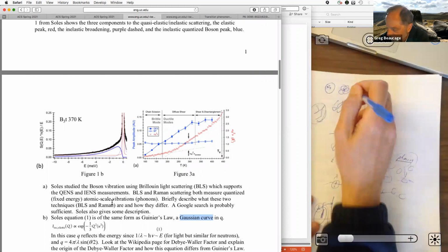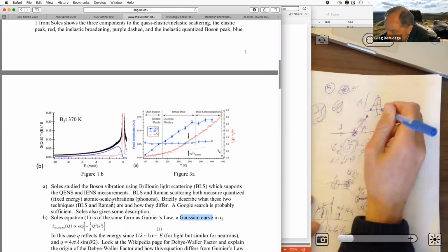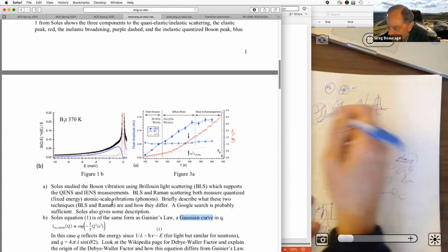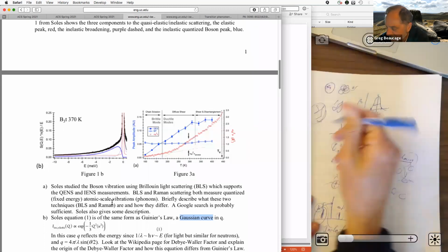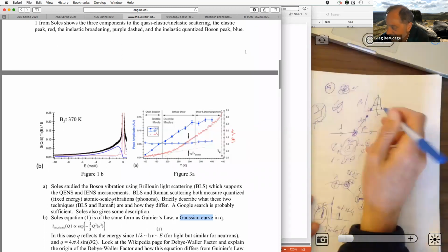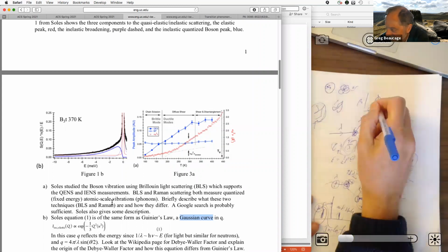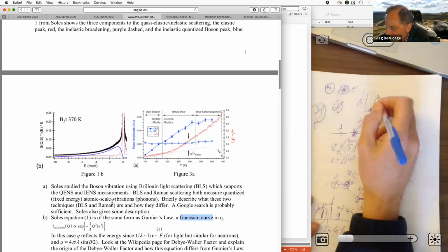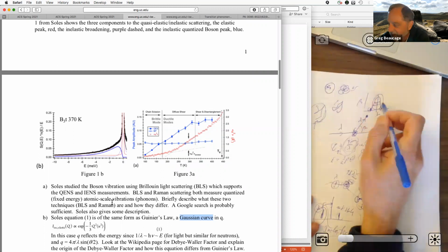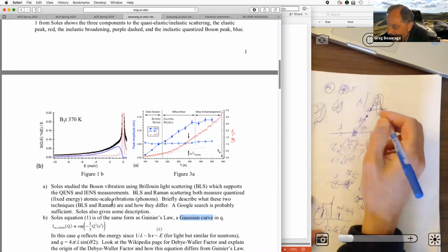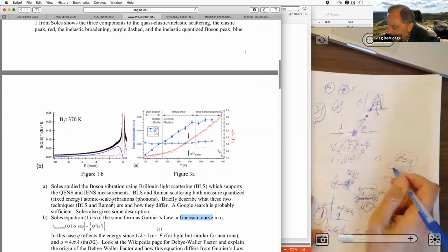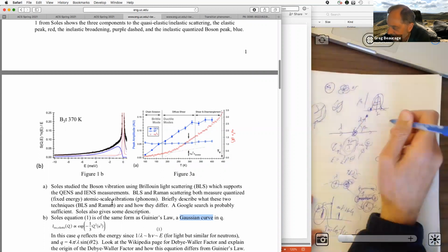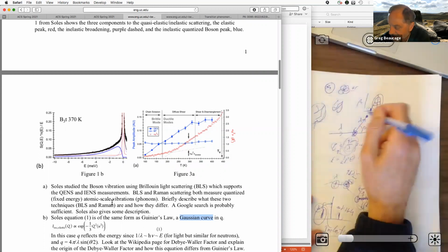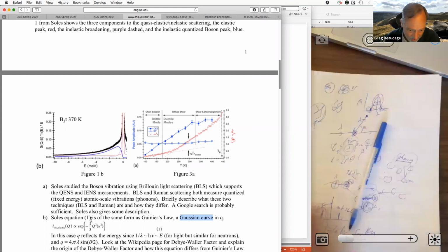So the truncation will be sharper for a sphere than it will be for an odd shaped object, right? But it will be broader for a polymer coil. But it turns out the truncation doesn't matter that much as long as you're looking at short distances here. So in this region where Guinier's law applies, it's okay. And the same thing goes for these phonons, right? The atoms are moving, but they're kind of restricted in space. So they're also going to have a truncation. So maybe this Debye-Waller factor could fall apart, similar to how Guinier's law falls apart.